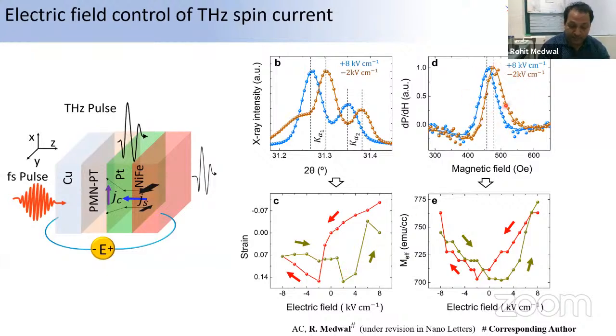We also did the FMR, the ferromagnetic resonance, and we can see that the same effect is being observed. Though because FMR is done at high field, because of saturation, we really don't get exactly the same separation, but we see the clear signature of this butterfly behavior as clearly observed in the strain behavior.